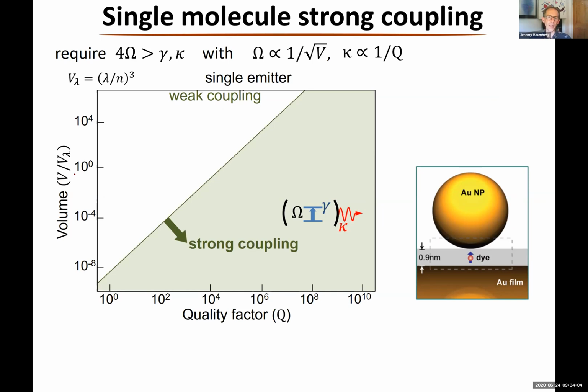So one of the things that we tried to do is to go to this strong coupling regime for a single molecule. As I said, this light matter coupling, which is what controls this, scales as 1 over the square root of the volume. To get the light matter coupling, I need my emission line or absorption line to split by this amount in strong coupling, but I need the line width, which is set by the losses in the system, to be small enough. So this is the problem of strong coupling, and we want to make this work at room temperature because we're interested in looking at the effects with chemistry.